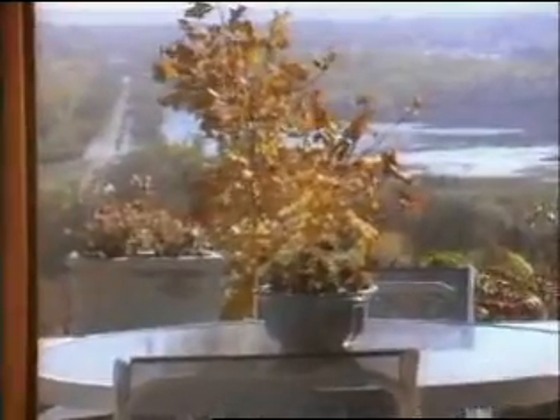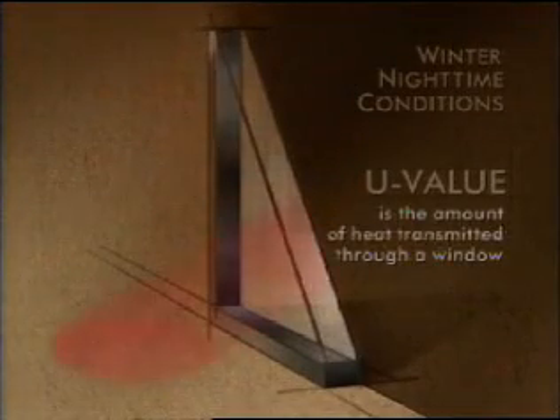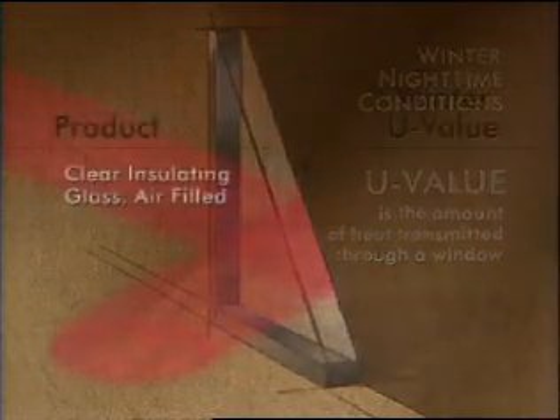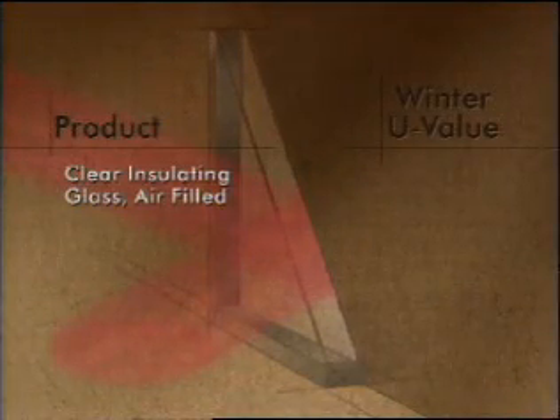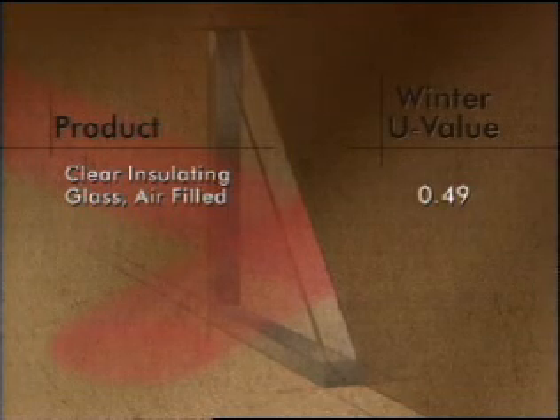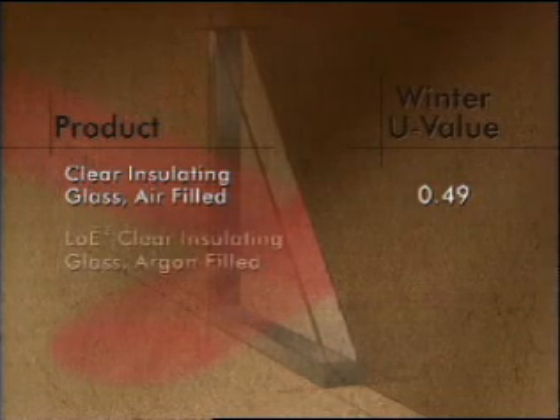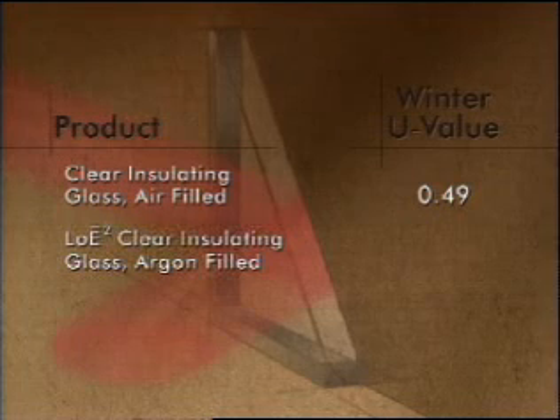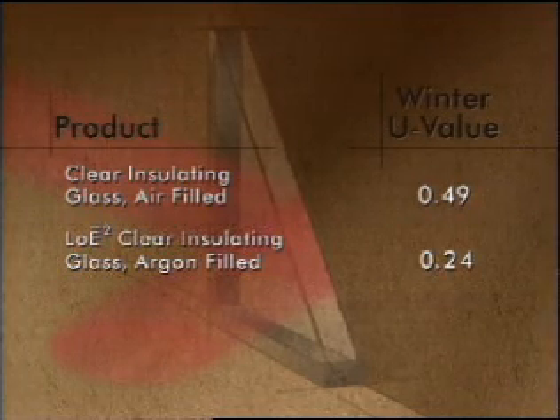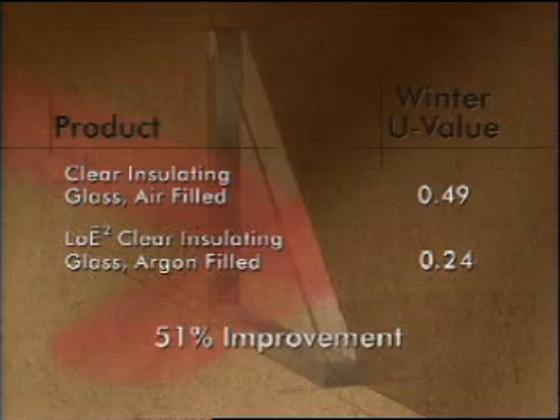Because insulating glass is the heart of the residential window industry, this is what you need to know when choosing a window. The U value is the amount of heat transmitted through a window. A clear, air-filled insulating glass unit has a winter U value of 0.49. A LoE² argon-filled insulating glass unit has a winter U value of 0.24, a 51% improvement.